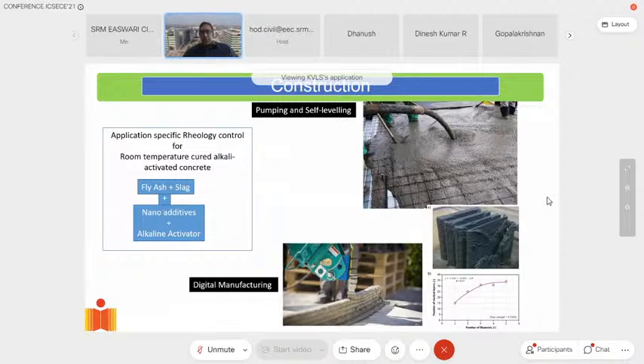By playing around with the rheology, I can produce concrete that flows like water, and you see that self-leveling, self-consolidating concrete or self-compacting concrete being produced here. This is concrete that flows like water. It fills the formwork under its own weight. There's no need for external vibration. At the end of the day, I'm able to achieve a concrete which is as strong and as durable as a concrete that is produced conventionally.